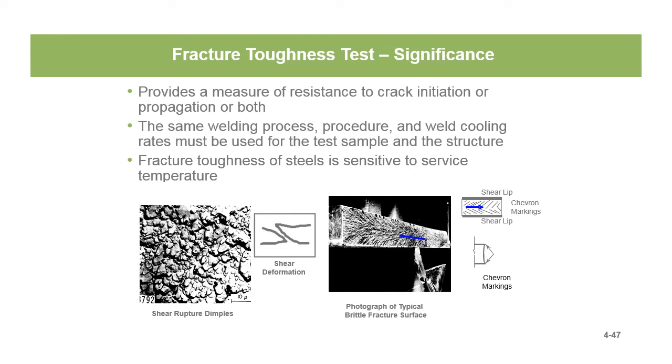There's a thing called the ductile to brittle transition temperature in the iron carbon system, and the way a steel reacts at 89 degrees in the West Texas sun is not the same way that steel is going to react in Alberta in January when it's minus 35 degrees Fahrenheit out. That same steel that is tough as hell in the West Texas sun is going to shatter like glass in northern Alberta in January.